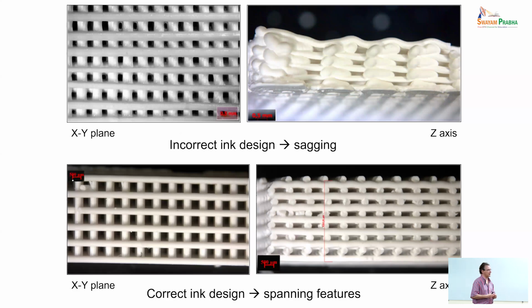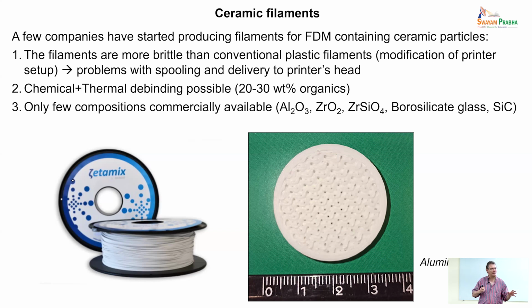So you can see here, for instance, what it means not to be able to control the rheology properly. This is a bioceramic scaffold, and this is the XY plane. So you're printing like this and looking in this direction. It looks very nice. But if you look in the cross section along the Z-axis, you can see that you have collapse of the struts or the filaments, because the recovery of the viscosity after releasing the stress was not fast enough. And if you optimize your rheology, then you're able to retain the structure that you want in your final part.